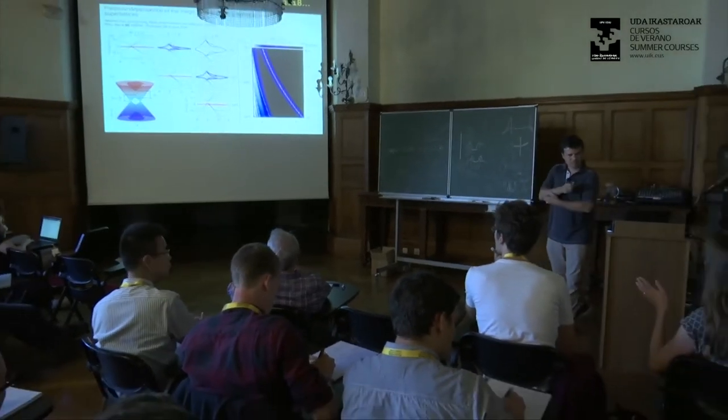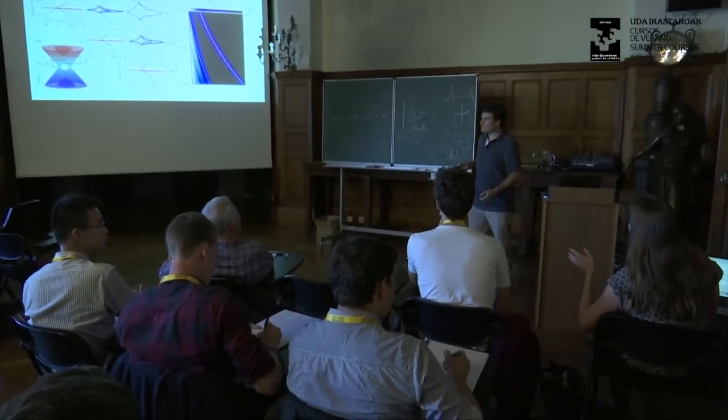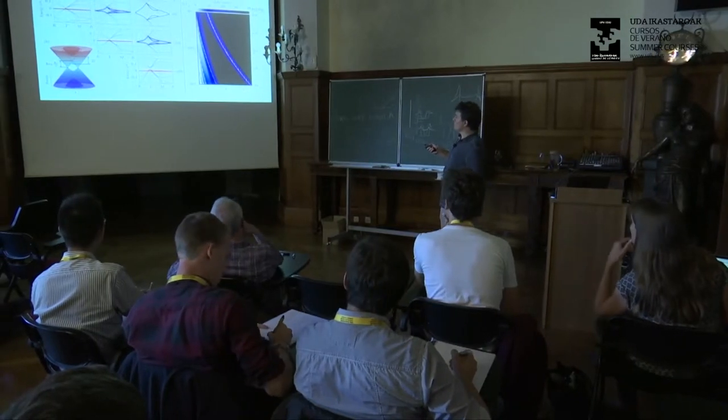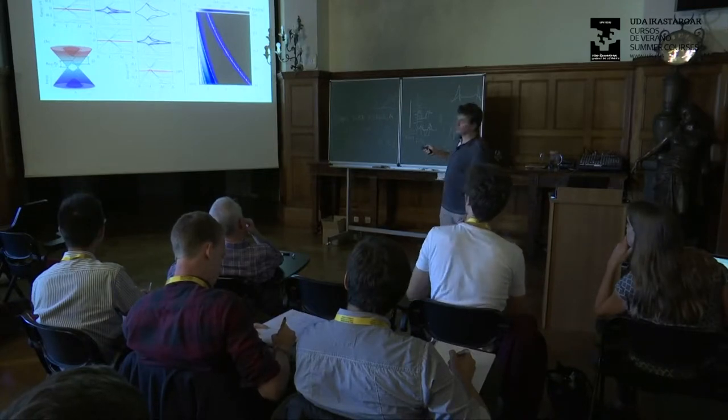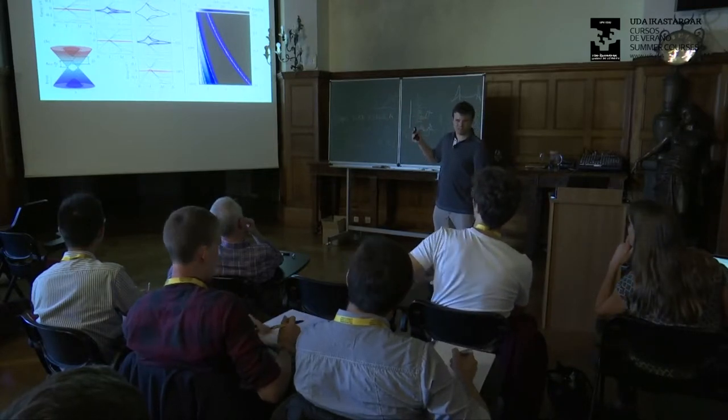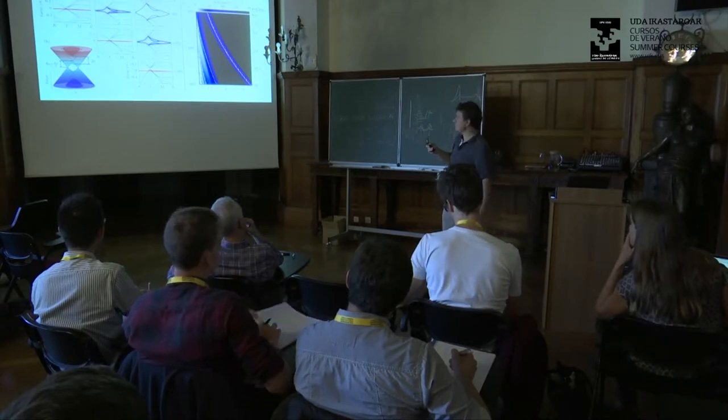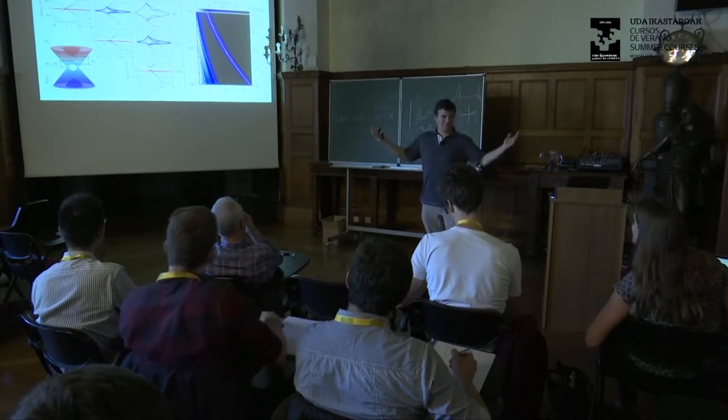Yes? So what range of angles can they go over and see this? Okay, they can go over pretty small angles, probably. These pressures are pretty high for the type of techniques that they had, so in practice they could only go a little bit. You see, they had 1.27, which is quite close to 1.1. Ideally, you would want to go to 3 degrees or something like that.